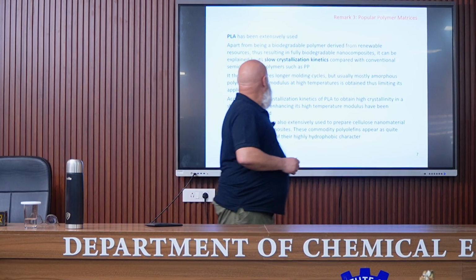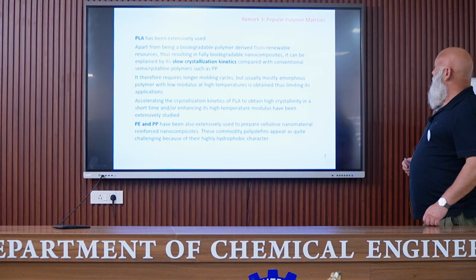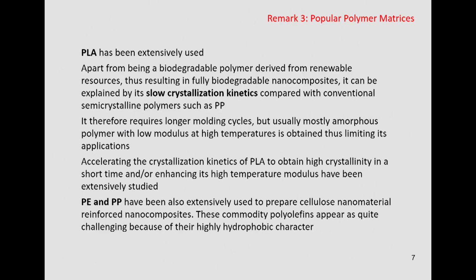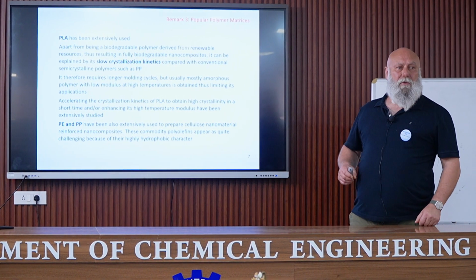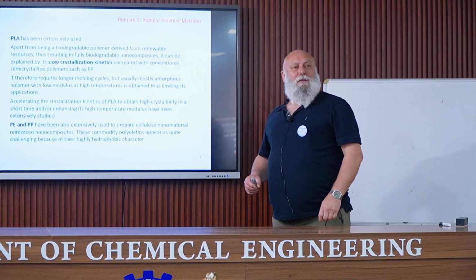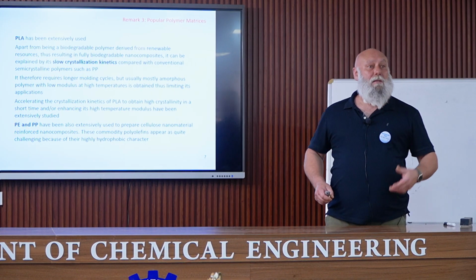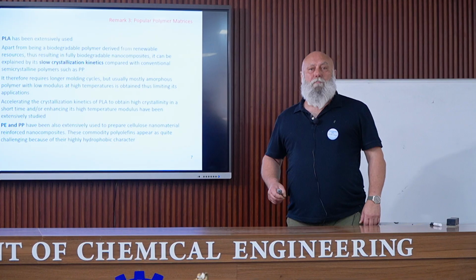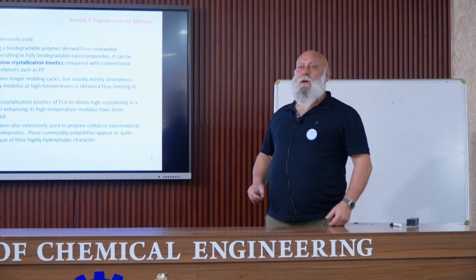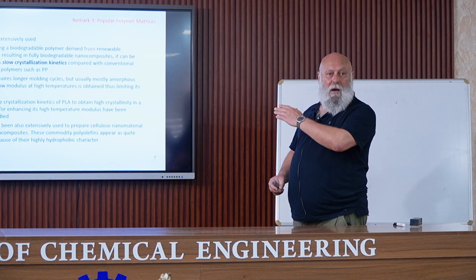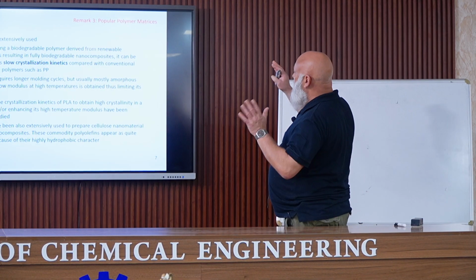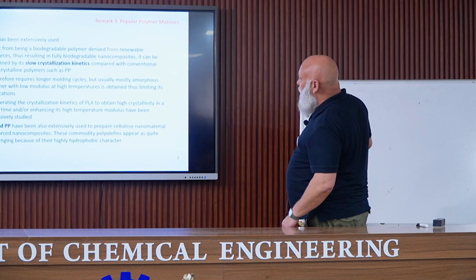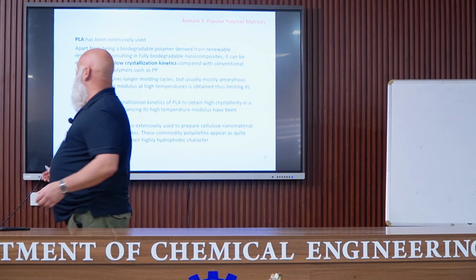Remark number 3. PLA, polylactic acid, has been broadly used. Of course, it's appealing because PLA is considered a biodegradable polymer, but it is not. It is biocompostable only, and only in industrial compost. I don't like PLA, I have to tell you. I don't like it because it is based on food resources, on corn, and the properties are very poor. It's a very brittle polymer, and the Tg is very low, around 60 degrees. I don't like it.